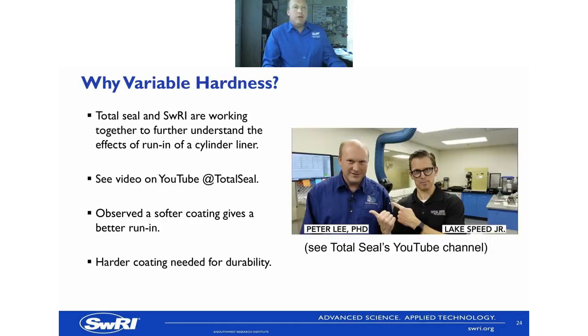So why variable hardness? Why have we now moved from that piston ring into a variable hardness coating for rings? Well, Total Seal and Southwest are working together to further understand the effect of the run-in of cylinder liners. So if you want to have a well-sealed liner, you need to make sure that you've got basically as little gap as possible between the ring and the liner. And to achieve that, you need the parts to run in very effectively and very smoothly.